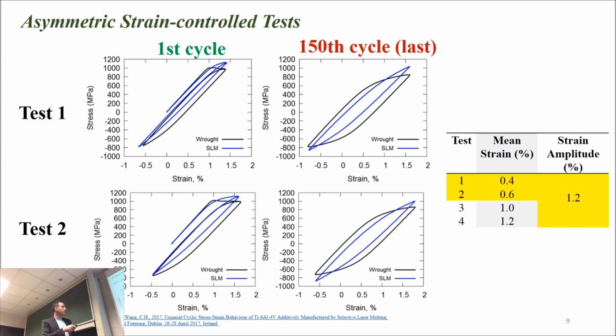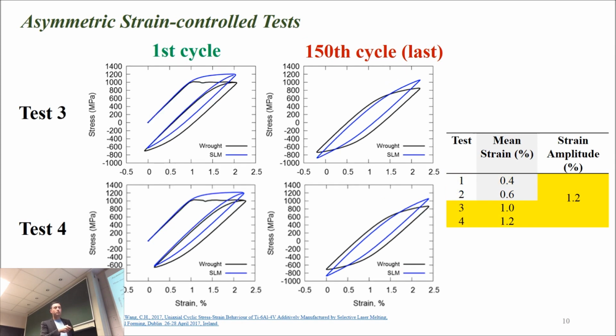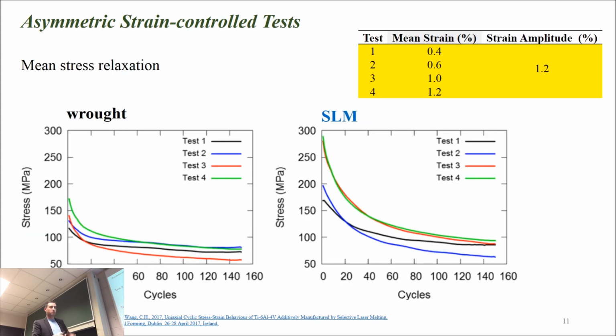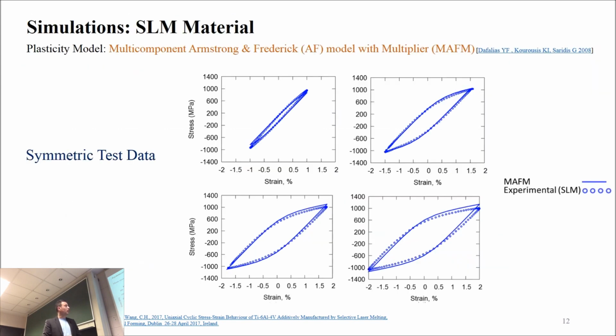What we see here, of course, is that first of all someone will observe that there is a higher stress level, which is identified from these graphs here. So we see the blue line which corresponds to SLM, so we have a larger hysteresis loop, which is evidently happening here as well. And another thing we observe is how quickly these residual stresses are relaxing for the SLM materials compared to the wrought metal. So this is an indication that, at least with these preliminary results we obtained, this material is highly likely to perform much better under high cycle fatigue.